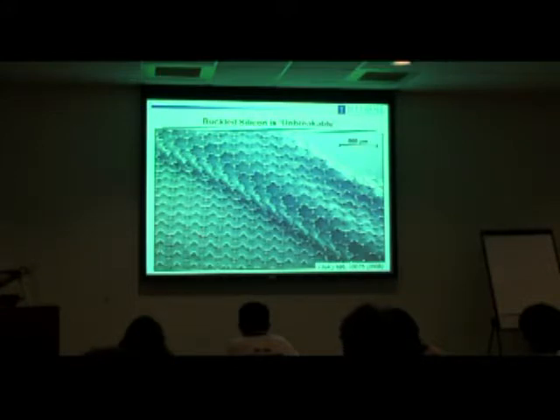So this is a thin sheet nanomembrane of silicon, structured into this mesh, number one. And then number two is by controlling the surface chemistry of the underlying silicone rubber, you can induce selective bonding of the silicon only to these island regions. So if you do the bonding of a mesh like that on a piece of silicone that's pre-stretched, and then you relax it, what happens is that the interconnecting ribbons deform out of the plane to form these kind of arc-shaped structures that accommodate all of the relaxation of pre-strain in a way that strain isolates these islands.